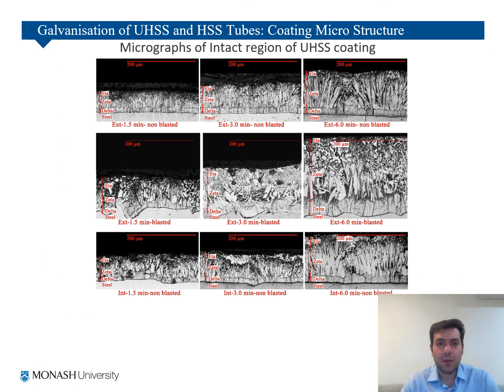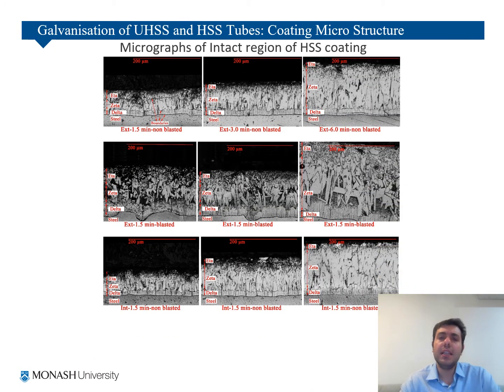These are the micrographs of UHSS tubes, and as you can see, the galvanizing has 3 layers, eta, zeta, and delta, and it increased the zeta layer by increasing the bath time. And that zeta layer is actually brittle and makes the coating brittle and not suitable. So it's better to keep the bath time shorter and not sandblast, because as you can see, by sandblasting, the coating thickness increases in the zeta layer. The same thing happened in high strength steel coated tubes, as you can see here. So it's better to keep the bath time short and not sandblast.